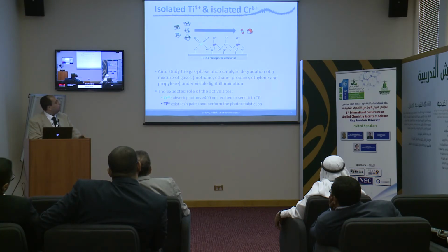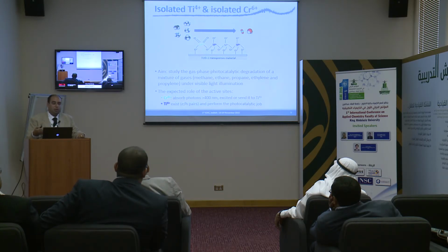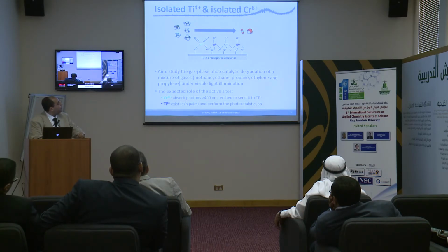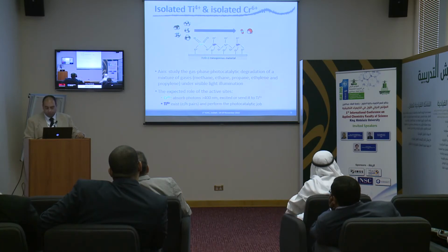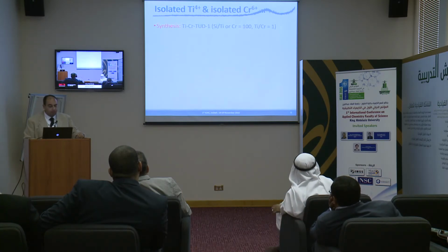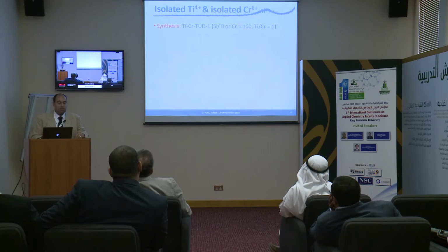If you increase the chromium loading to more than 1%, you will start to get some kind of nanoparticles of chromium oxide, chromium-3 oxide. And this one has been reported many times to be not photocatalytically active. So you really have to keep this one under 1% and do this trick just to enhance the photocatalytic activity of this material. Well, so this is titanium chromium TUD1.